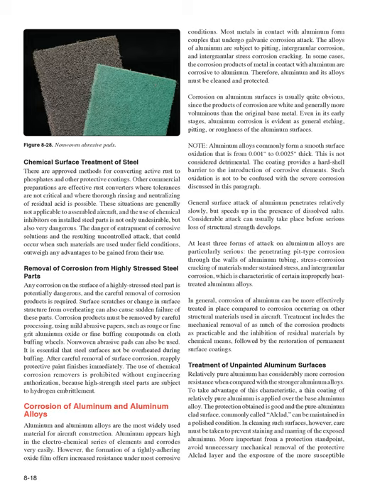Removal of corrosion from highly stressed steel parts. Any corrosion on the surface of a highly stressed steel part is potentially dangerous, and the careful removal of corrosion products is required. Surface scratches or change in surface structure from overheating can also cause sudden failure of these parts. Corrosion products must be removed by careful processing, using mild abrasive papers, such as rouge or fine grit aluminum oxide or fine buffing compounds on cloth buffing wheels. Nonwoven abrasive pads can also be used.